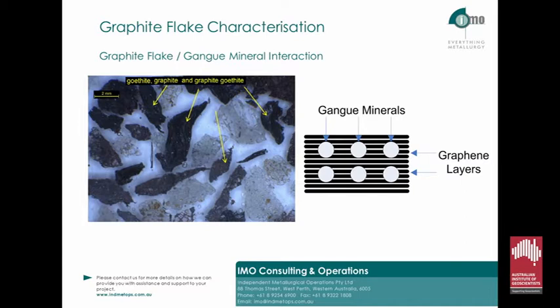If there is gangue within the flake, then it becomes more difficult to maintain the flake distribution and achieve a high-grade concentrate. Once the gangue is removed from the flake edges and the final flake concentrate is recovered, it's then the flake to gangue ratio which will ultimately determine the graphite grade. The flake can be upgraded, however it's then via dissolution of the gangue within the flake and often with a combination of caustic and acids. This then makes the process expensive and often not economical.